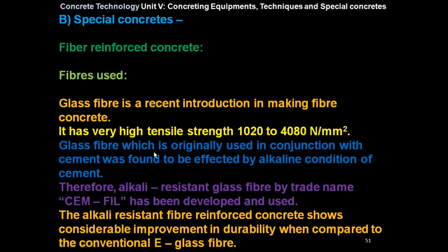Glass fiber, which is originally used in conjunction with cement, was found to be affected by alkaline condition of cement. Therefore, alkali resistant glass fiber by trade name Cem-FIL has been developed and used. The alkali resistant fiber reinforced concrete shows considerable improvement in durability when compared to the conventional E-glass fiber.